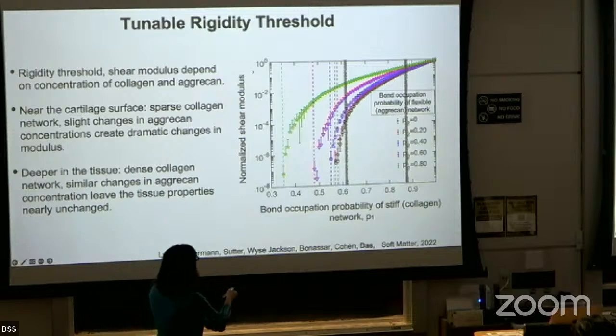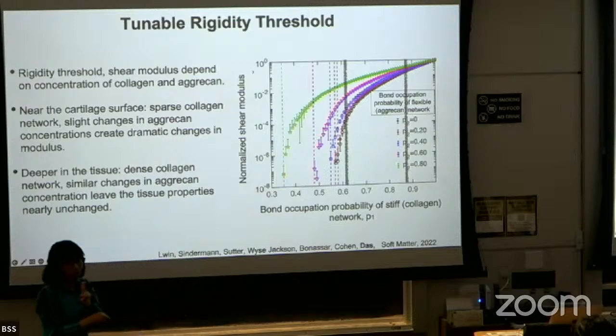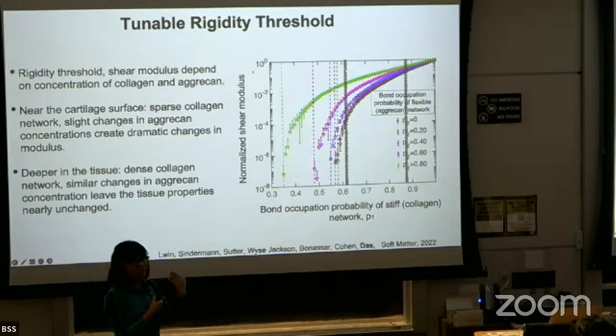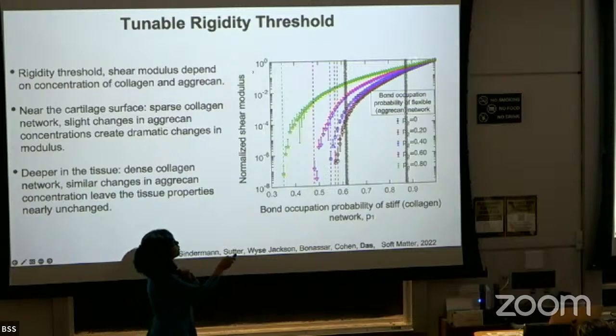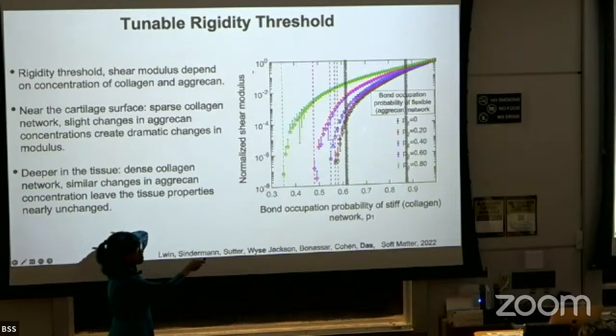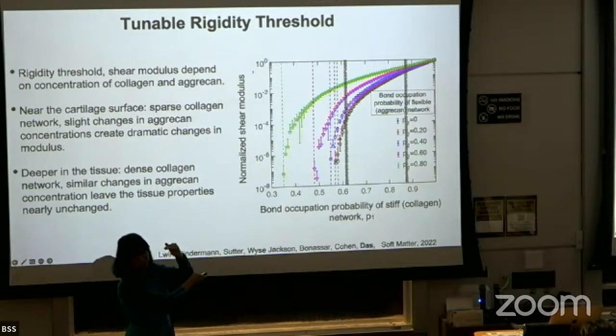Now you can ask, why have I drawn two dashed lines? That's for the following reason. If I was in a region of cartilage very close to the bone, my collagen network and aggrecan network are both super dense. There, if I keep the collagen density fixed and decrease the amount of aggrecan, the change in shear modulus is very little. But if you're close to the joint, then the collagen network is above its percolation threshold, but it's not that dense.